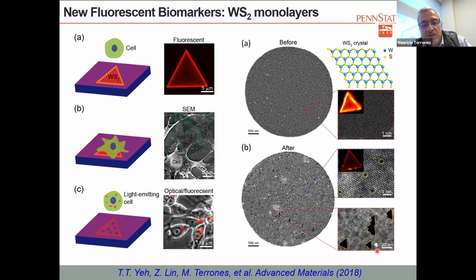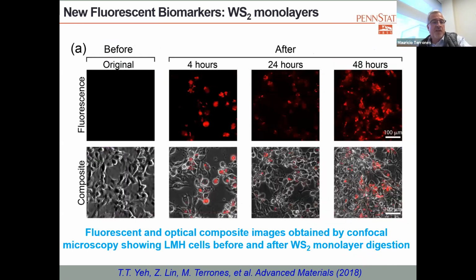That's a 30 nanometer scale bar. But they have ingested it. One thing that we noted is that before ingestion, the cells don't fluoresce, but after 4 hours of ingestion you can see the cells shine, and after 48 hours they keep shining. One thing that is happening here is that the cells start to divide and replicate. And the nice thing about this is that even after 2 to 3 generations, the fluorescent material was passing from one generation to the next.